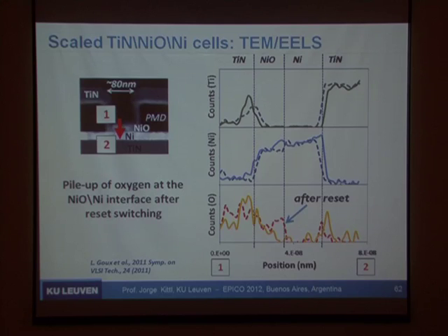We could also see some evidence of TEM yields, basically showing anodic oxidation, in this case at the nickel oxide interface. I would say that this yields evidence, but you have to treat it very skeptically, because you're thinning down a TEM specimen and trying to do chemical analysis very locally with a beam that's modifying your sample. We found these results, and we think they're probably correct. I would not say this is the most drastic evidence of anodic oxidation, but it is consistent with anodic oxidation.